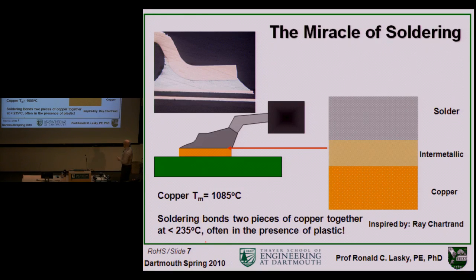Well, one of the things that happens in soldering is at the melting temperature of solder, and this is again mostly activated by the tin, the solder forms an intermetallic, a tin-copper intermetallic that not only makes a mechanical bond but makes an electrical bond. And the intermetallic is a requirement, but if the solder is too hot or your soldering time is too long and the intermetallic gets too thick, it can cause problems, most commonly fracturing.